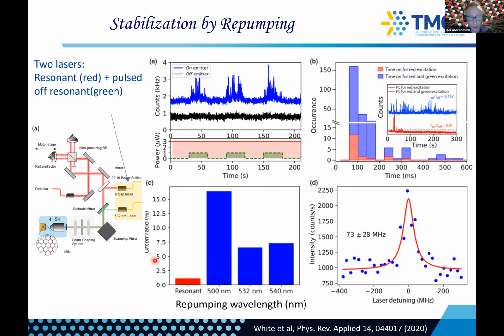And so this is the probability to excite an emitter. So this is the probability to detect fluorescence, resonant fluorescence, under resonant excitation conditions. And you can see that by repumping, we basically increase it by an order of magnitude. And so under this condition, you can actually record a resonant excitation spectrum, a properly coherent source. So, this is rare. If you're going to the lab tomorrow to try this experiment, be aware that it only works on about 10% of emitters. We are not sure why, and this is what we are basically studying now.